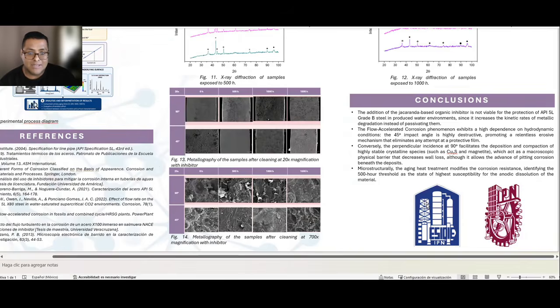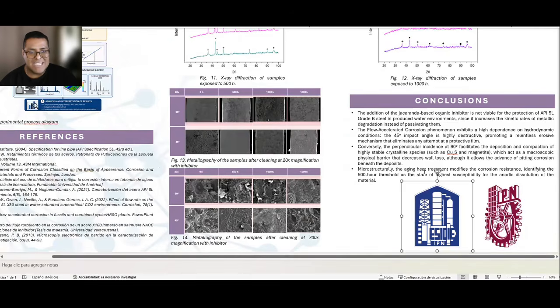Inversely, the 90-degree incidence facilitates the deposition of highly stable crystalline species, acting as a physical barrier that decreases the metal loss. Finally, microstructurally, the aging heat treatment modifies the corrosion resistance, and we identified the 500-hour threshold as the state of highest susceptibility for the anodic dissolution of the material.